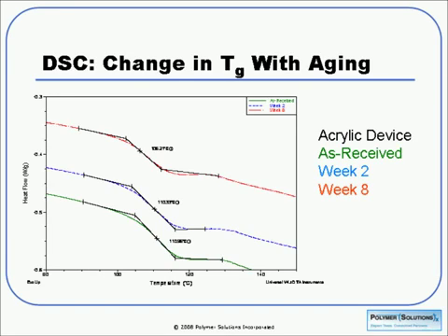And we can see that we're getting some droppage in our TG. It's going from about 111 down to 106. So this indicates that the conditions under which we're testing are actually starting to degrade the sample a little bit. So this is an easy way to get a handle on that. And again, it's a real small sample size. You may be able to do some other tests with other parts of that material that you were aging and still have those available after.